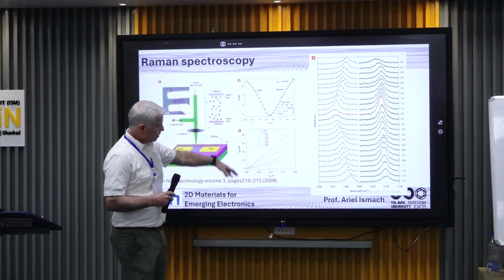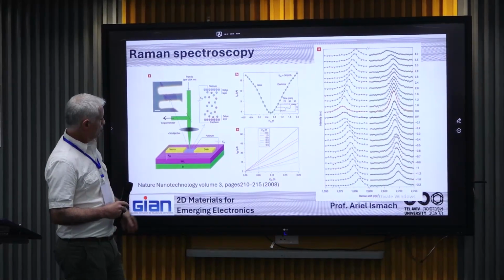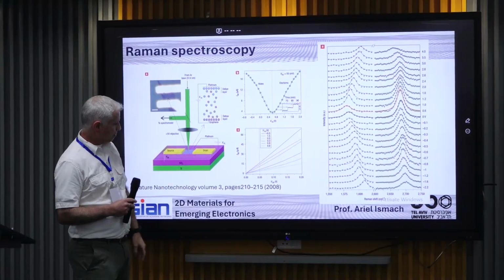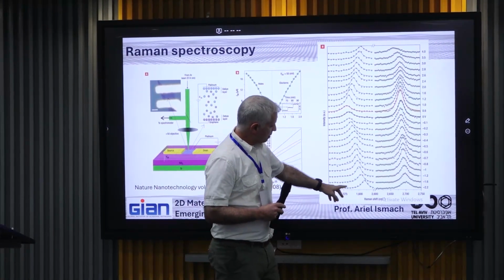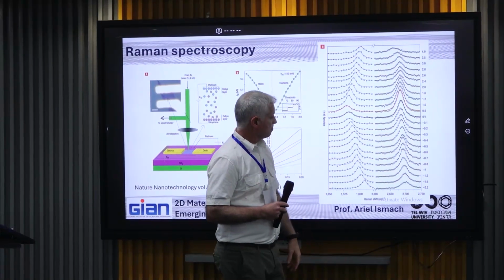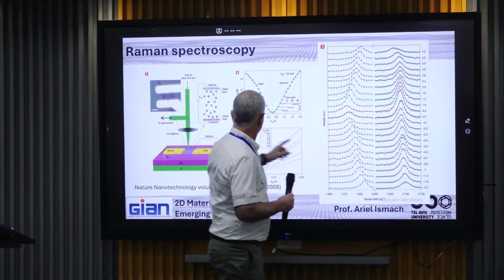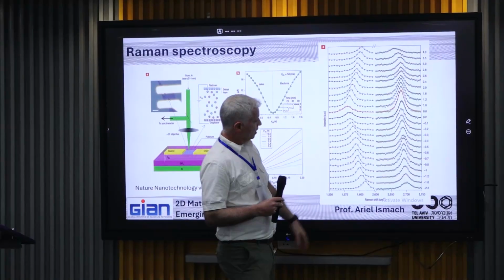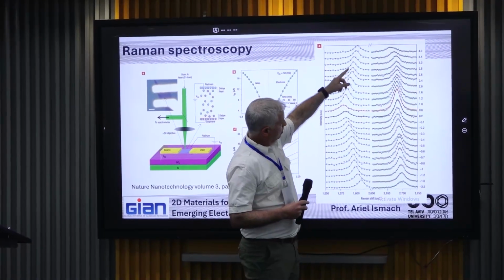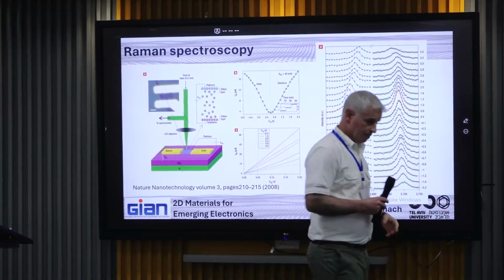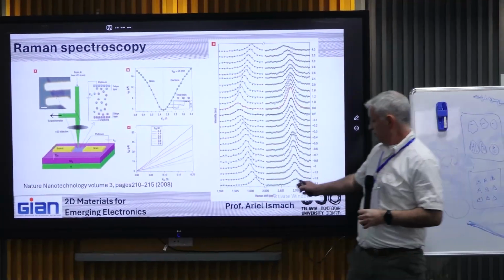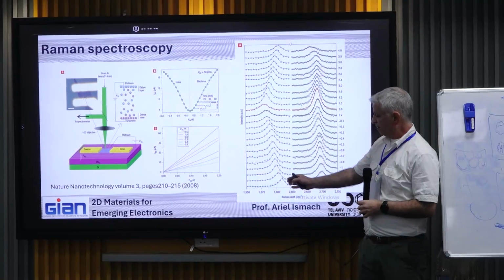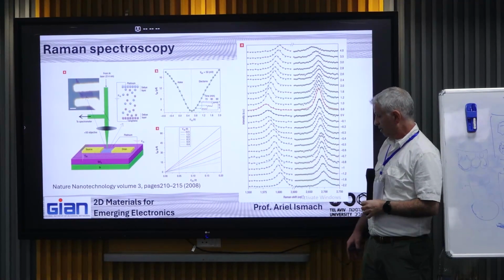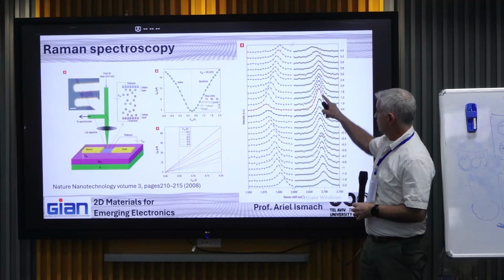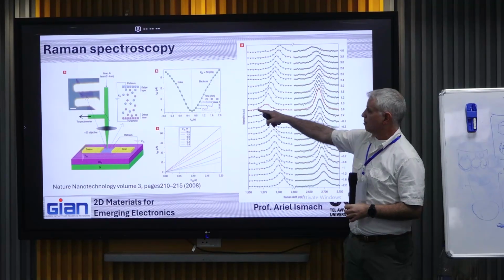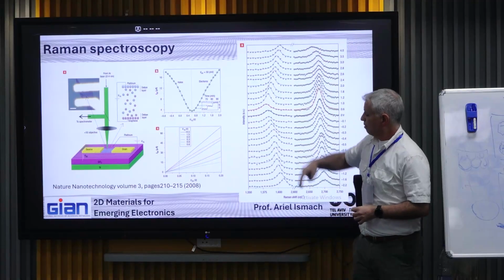Anyway, once you characterize the device and it works, you can start doing Raman in situ, applying voltage and analyzing. In this case, you can see the G mode and the 2D mode, the G prime mode, as a function of the top gate voltage. And you can see that the G mode moves according to the charge density. The larger the voltage, the larger the shift of the G mode position, as you can see here very nicely. So this is for zero gate, no gate. This is our starting point. And from that, you see how it changes dramatically.